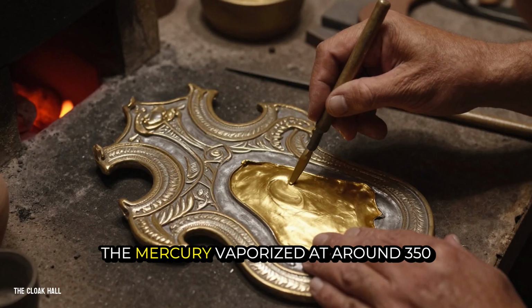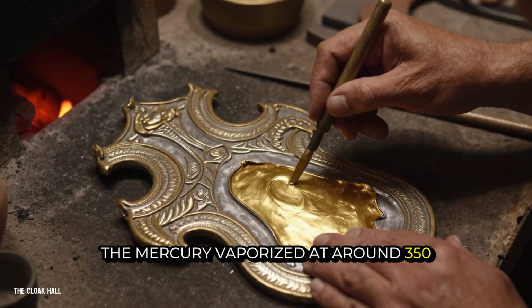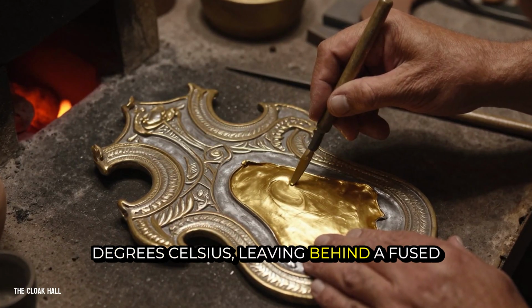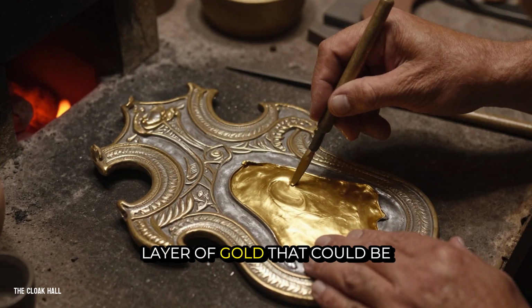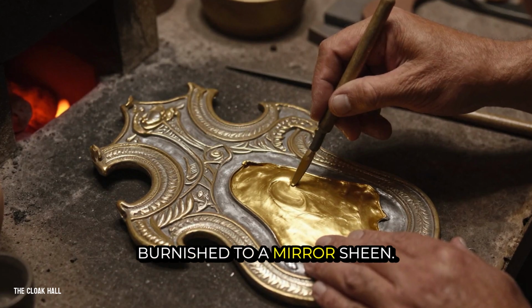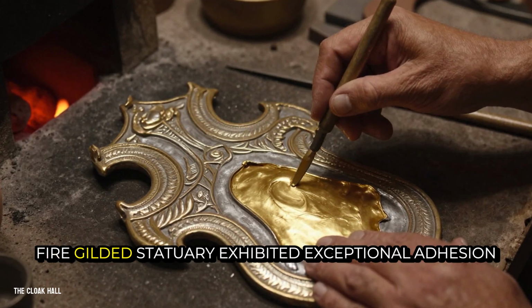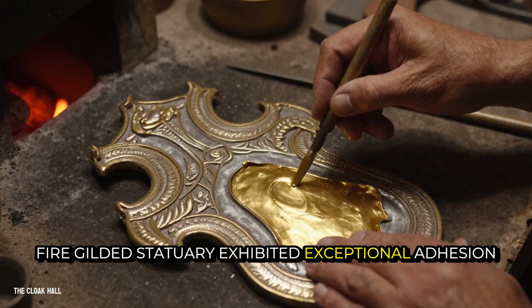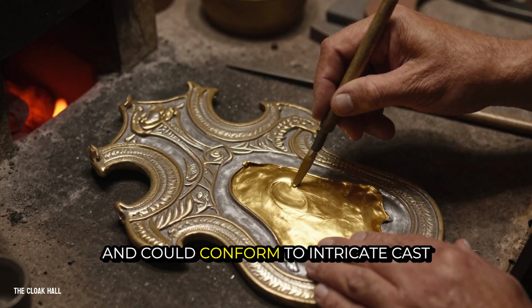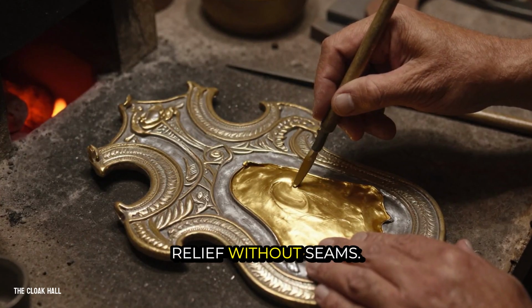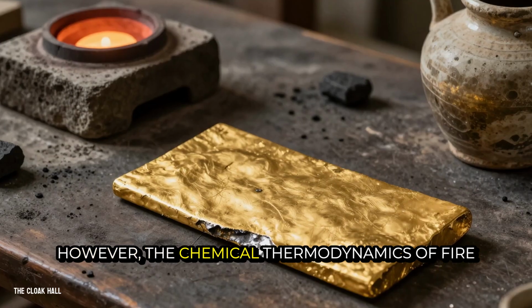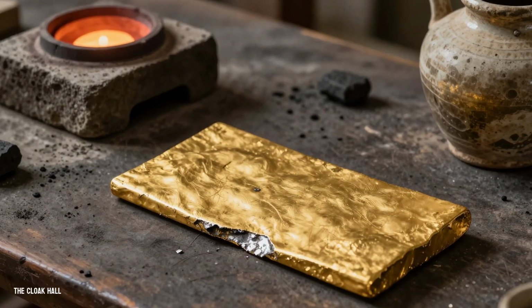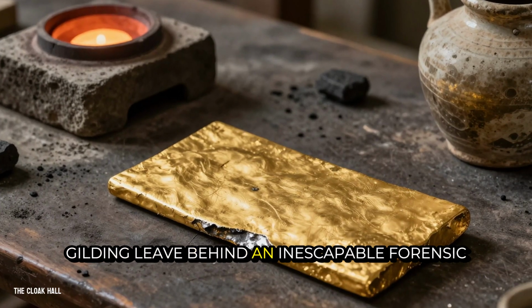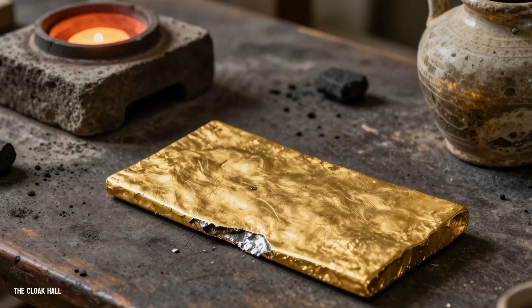The mercury vaporized at around 350 degrees Celsius, leaving behind a fused layer of gold that could be burnished to a mirror sheen. Fire-gilded statuary exhibited exceptional adhesion and could conform to intricate cast relief without seams. However, the chemical thermodynamics of fire gilding leave behind an inescapable forensic fingerprint.